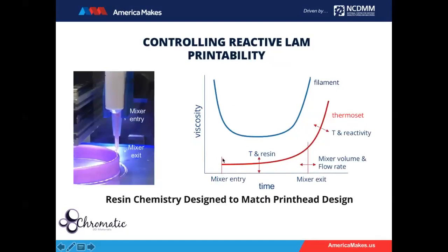So if you think about the viscosity that you might have when the material enters the mixer, and then the viscosity at the point that it exits, where it's just starting its reaction, what we can adjust is the resin chemistry to change how fast that viscosity increases. We can also use temperature, we can use catalyst, and we can also change the size of that mixer volume. And then when it solidifies onto the part, we can also adjust its performance there with the temperature again, as well as the reactivity. And so what we specialize in at Chromatic 3D Materials is how to design that resin chemistry to match the print head design to get the ultimate performance that's required in the application.